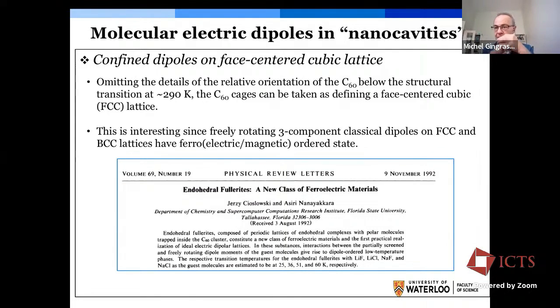And this is interesting in part because it's been known for 60 years that on the face-centered cubic lattice and on the body-centered cubic lattice, classical dipoles should exhibit a ferroelectric or ferromagnetic phase if they are freely rotating. And so this was already anticipated by the work of Cioslowski and Nanayakkara in 1992, where they argued that if one were able to encapsulate electric dipoles in fullerenes, one would be able to generate this kind of phenomenon, have dipoles in an FCC lattice. Of course, this is in a context where one is ignoring the cage deformation and the coupling between rotation and translation of the water molecules within the cage.